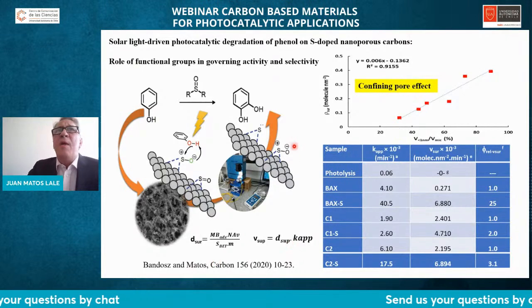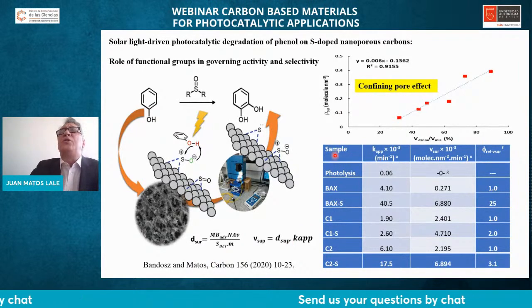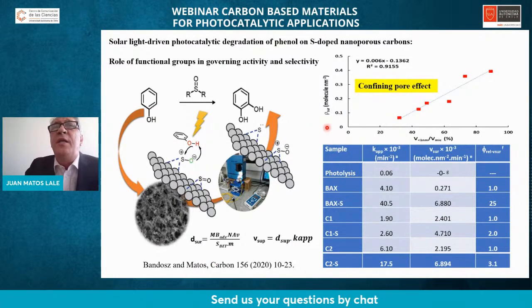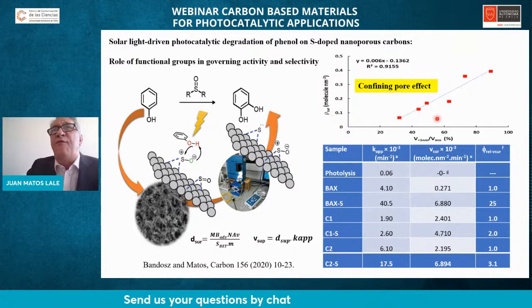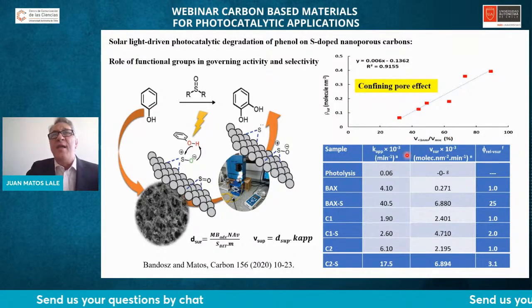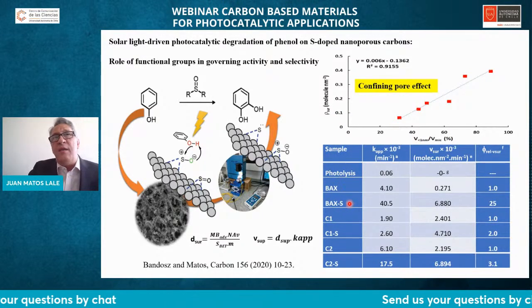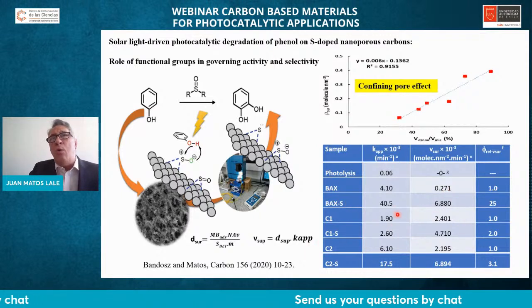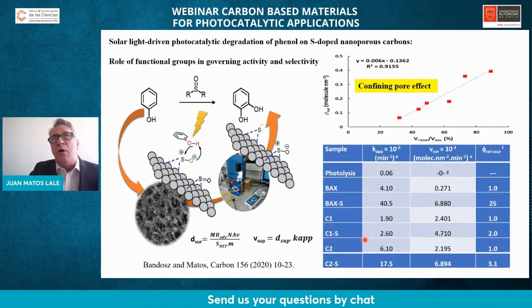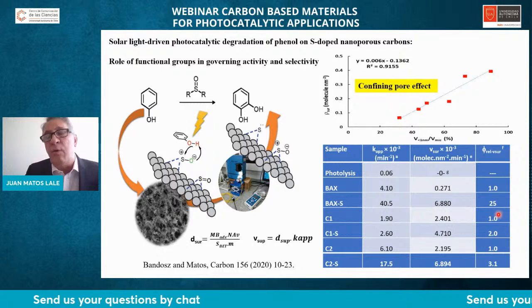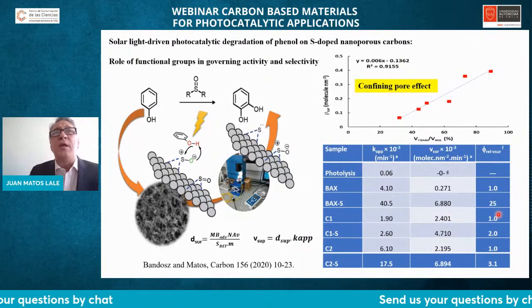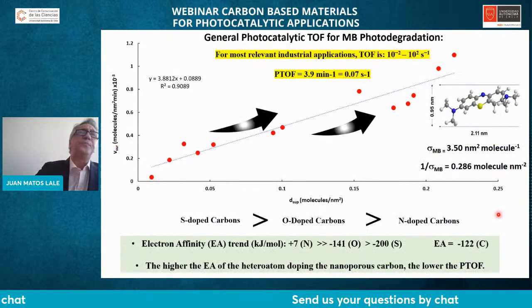And at the same time, we achieve a very interesting relationship between the surface density of molecules adsorbed as a function of the pore confining effect. In comparison, all the system in presence of sulfur shows a very high activity in the photodegradation of phenol.